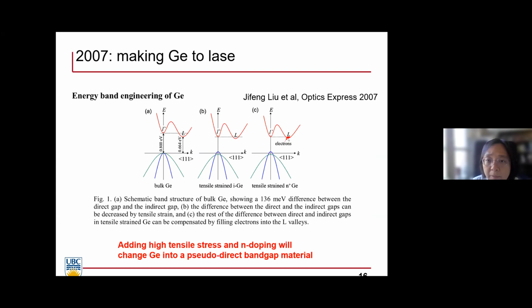closer. And then we can dope this germanium. So we have N-type doping to provide free electrons that occupy the L band. Then when we do current injection, electrons will split between the indirect and direct bands. And then we're going to have direct radiative recombination from the direct band. So that's not only an idea, it has been demonstrated.